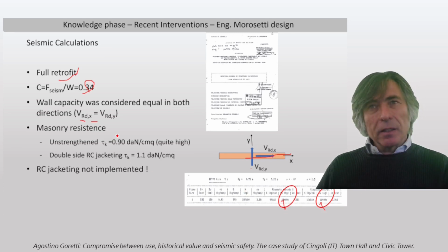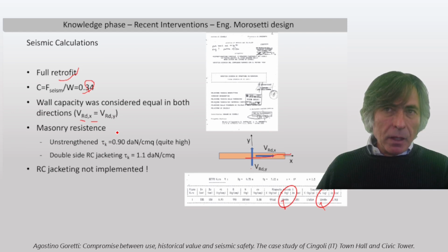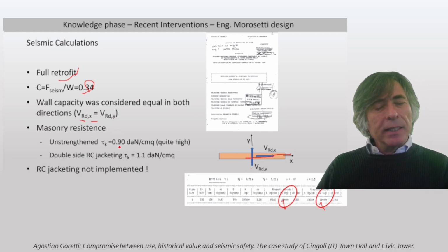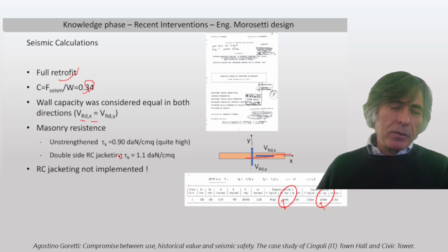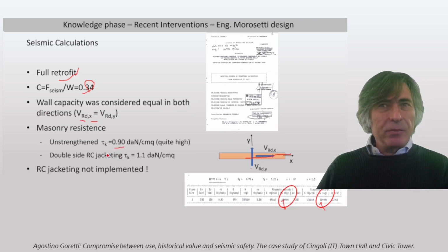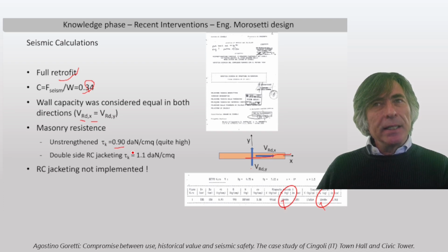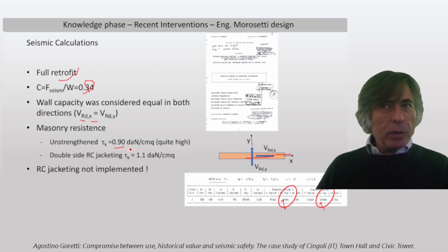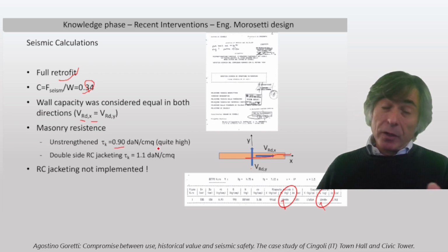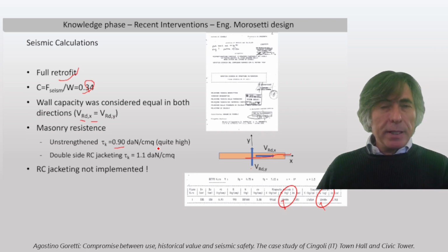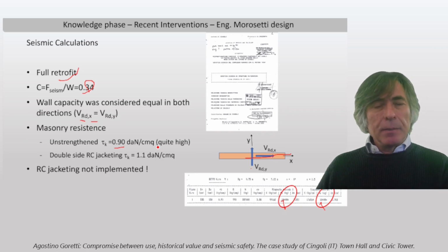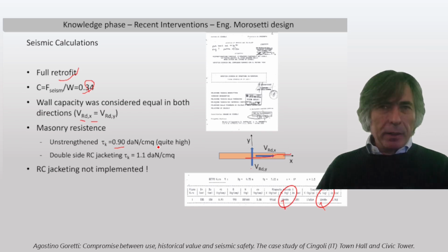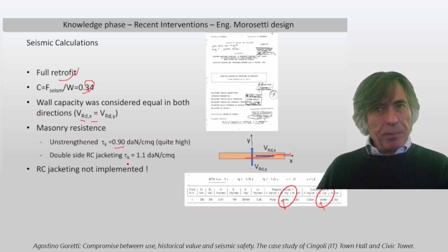As a second point, I found that the resistance of the wall that has been considered in the calculation is quite high. For unstrengthened material, it's 0.9 decanewton per square centimeter, which is about 9 tons per square meter. So it's a quite high value, typical of very well squared stone masonry with thin joints, and it's not really a proper value for irregular masonry with low resistance or degraded mortar.